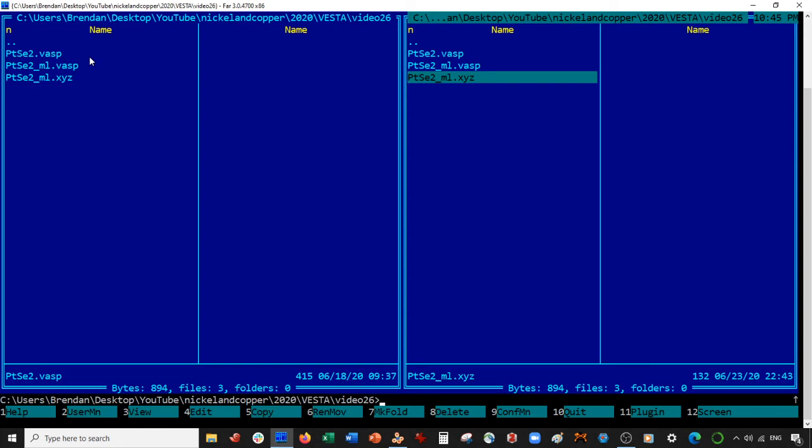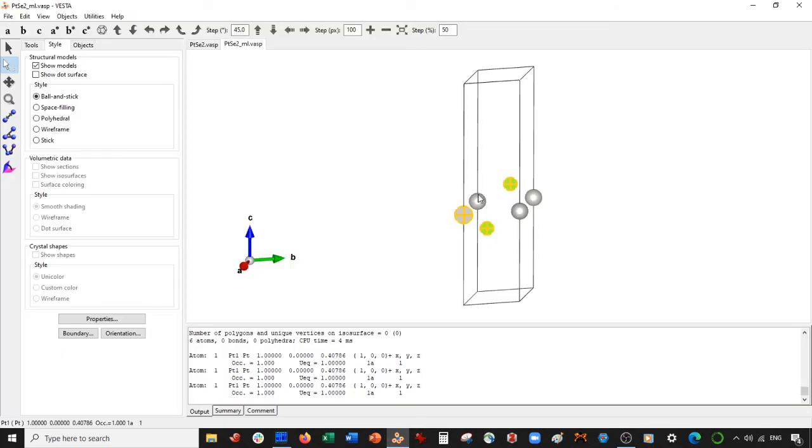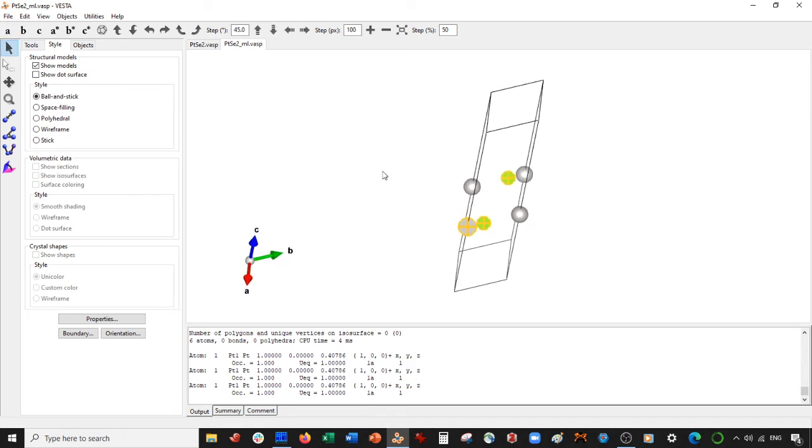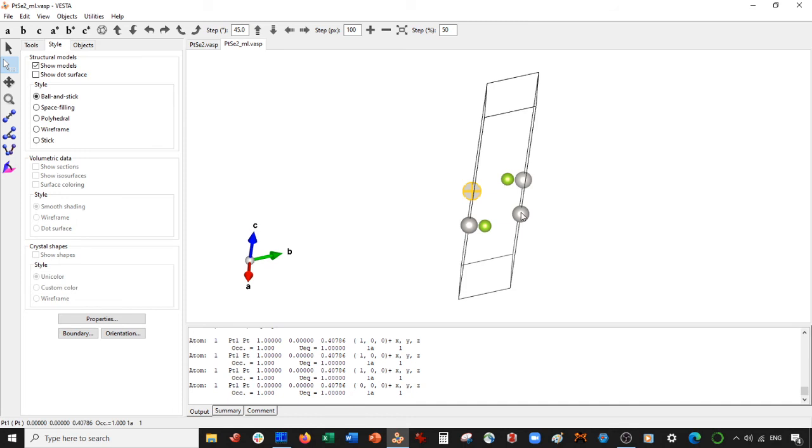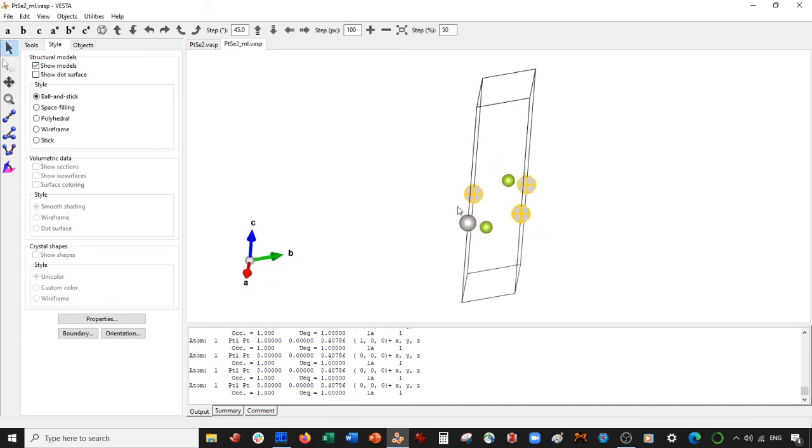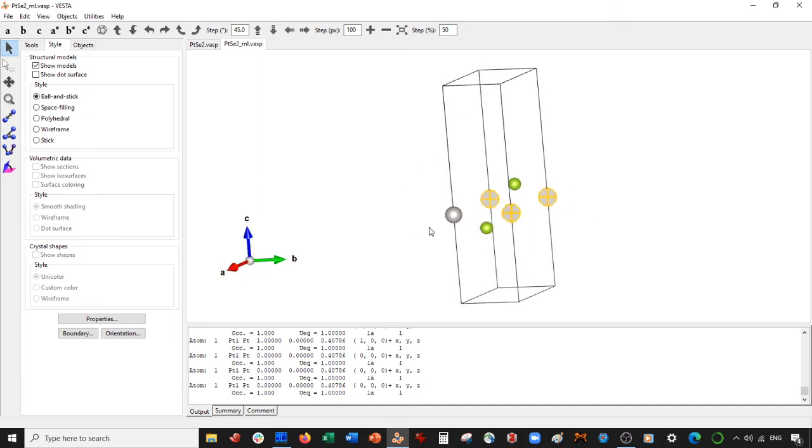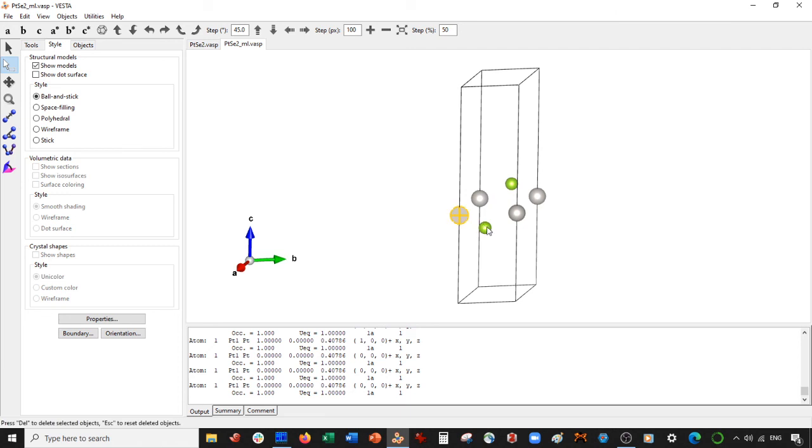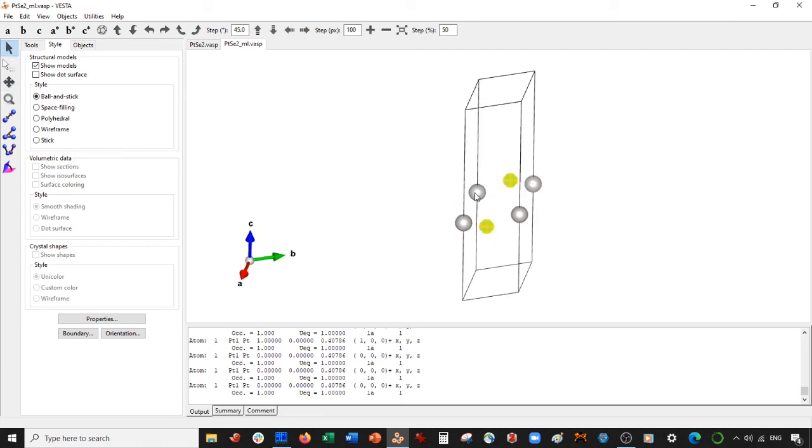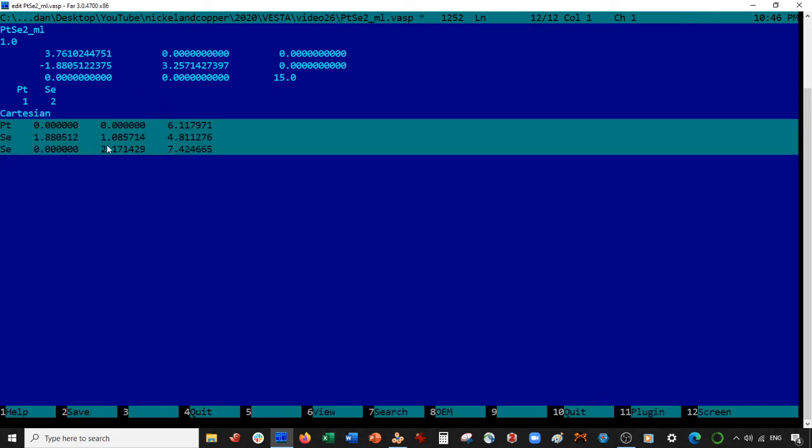You can also use these coordinates as well in your Quantum Espresso. These are the coordinates you use in Quantum Espresso, same as in the VASP file, except here you have to re-add the atomic labels. When you load these coordinates into Vesta with a unit cell, Vesta automatically populates these three. We did not have these three in our input file, Vesta automatically put them in. If I save this entire thing as an XYZ though, then what'll happen is if you put all of these atoms into Quantum Espresso, it'll crash because you're explicitly including the repeating atoms. Just to reiterate, there's only three atoms we're going to put into Quantum Espresso. It's going to be these three.